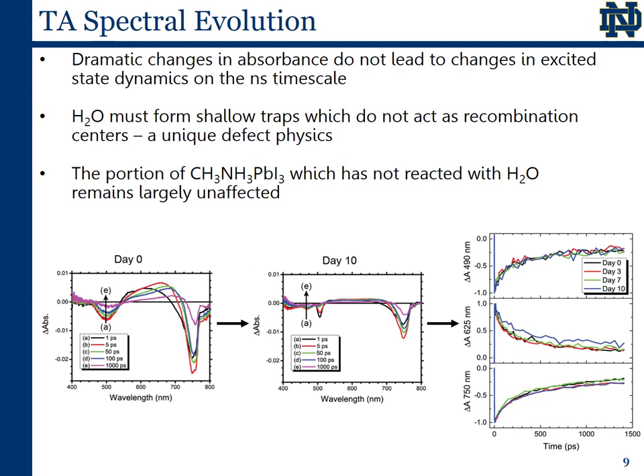Perhaps more interestingly, when investigating the recombination kinetics of the perovskite films, we find that, despite the dramatic changes observed in the optical absorbance, we see no observable changes in the excited state dynamics on the nanosecond timescale. This implies that water forms states which do not act as recombination centers, and that the methylammonium lead iodide which has not yet reacted with water remains largely unaffected by this degradation process.